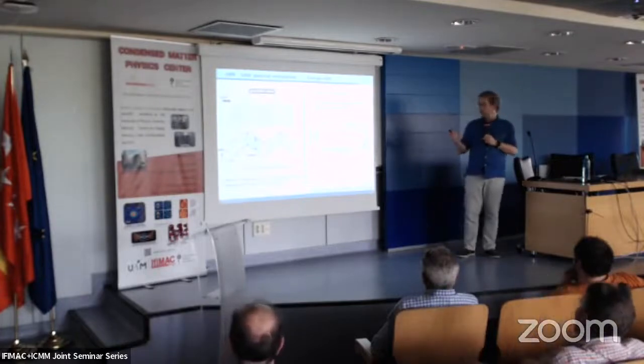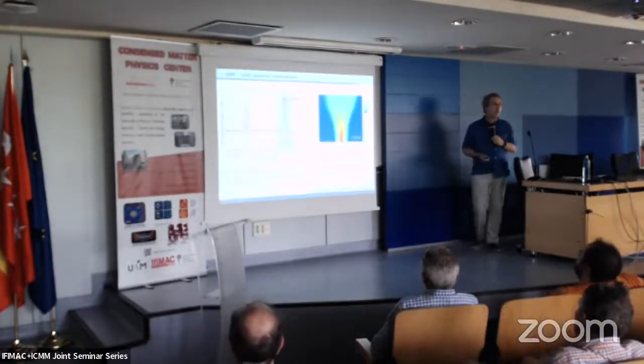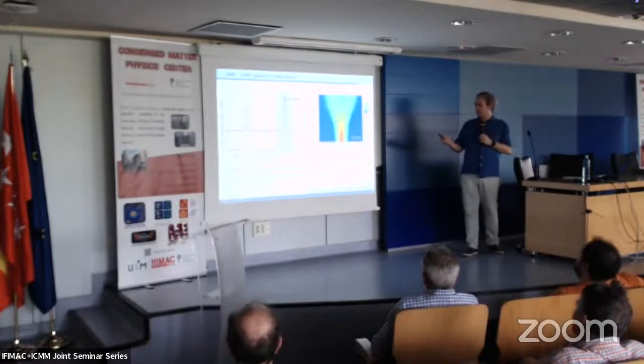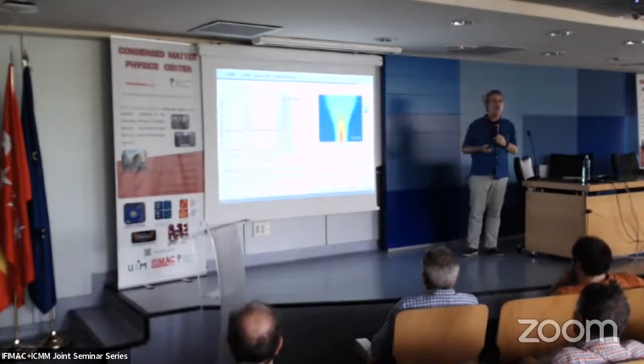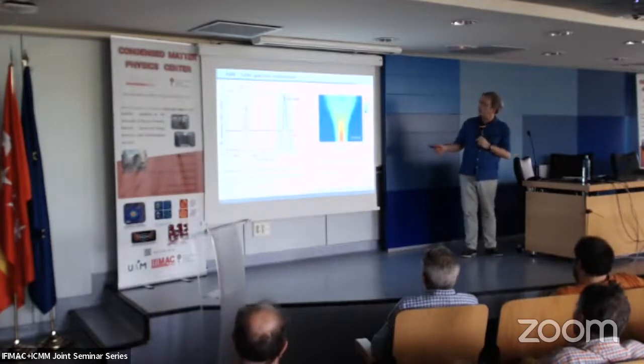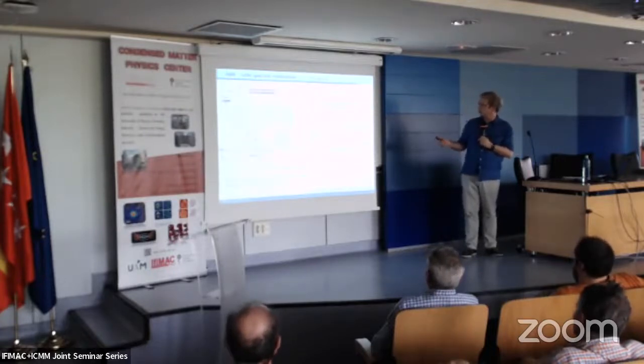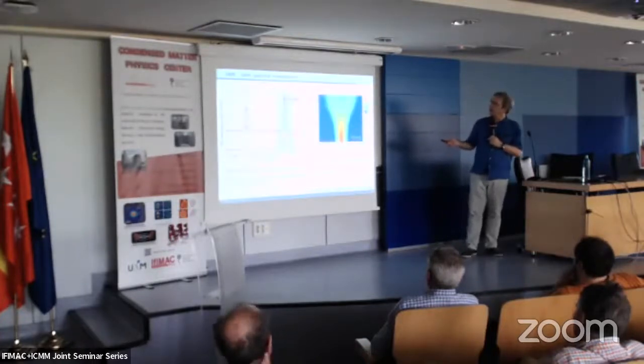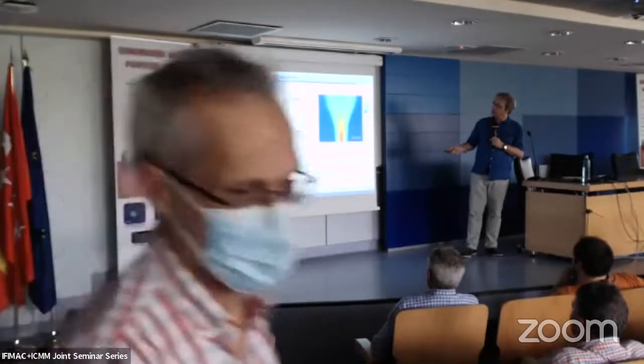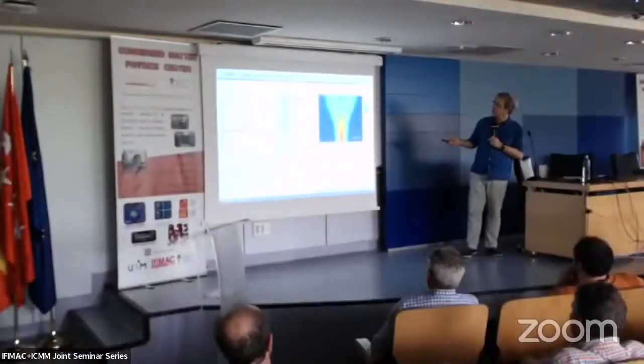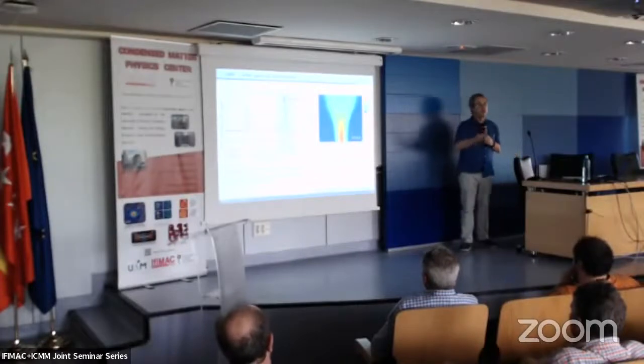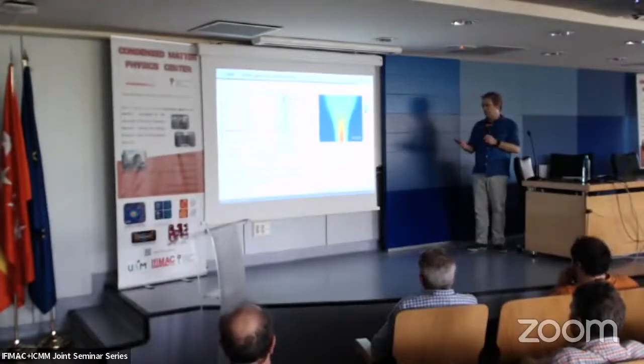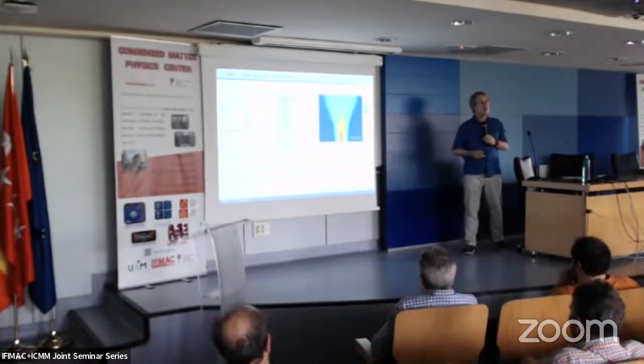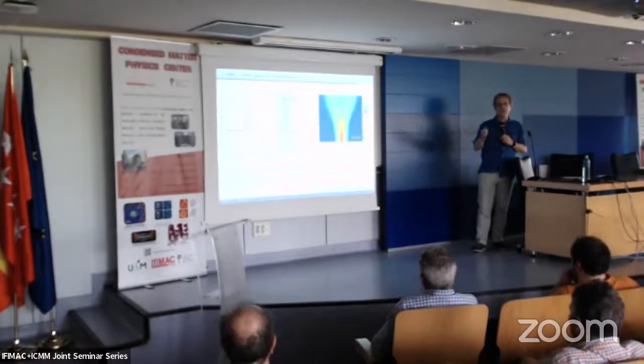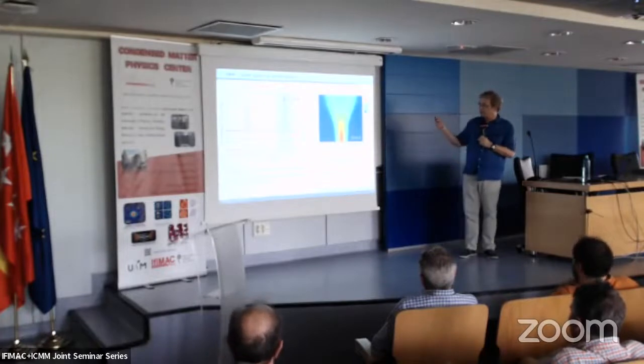What we can do also is to synchronize, for instance, the detection, where we can also only detect when we are at the left side, or only detect on the right side, depending on which phase of the surface acoustic wave. So in this kind of phase detection, you can really shift the energy emission as you like between these limits.